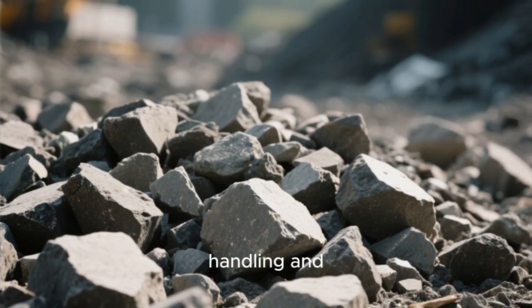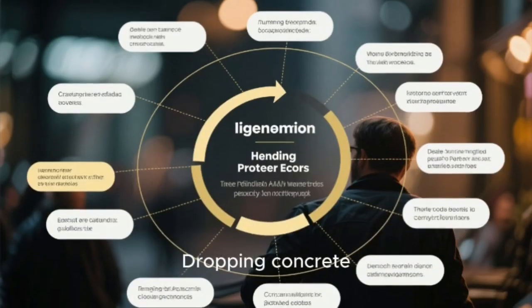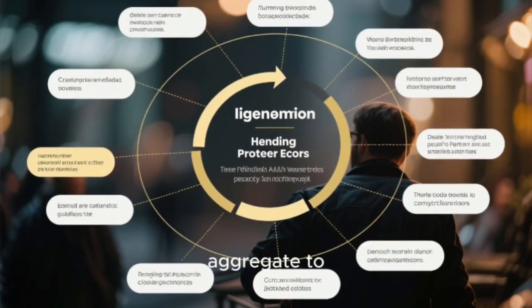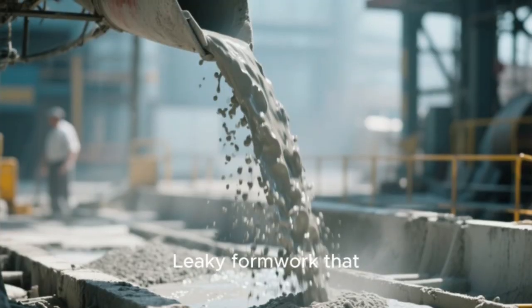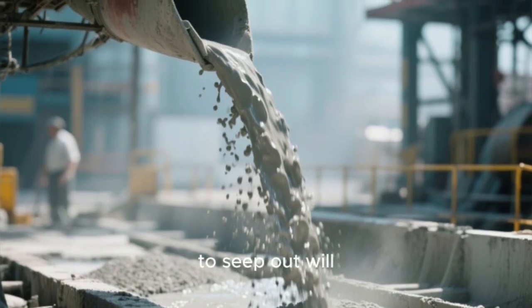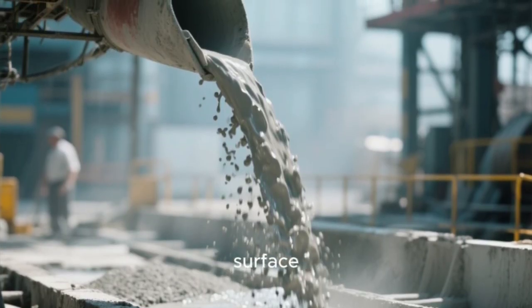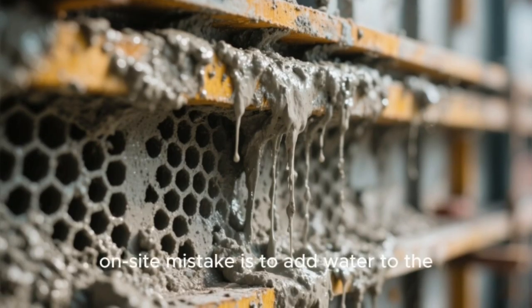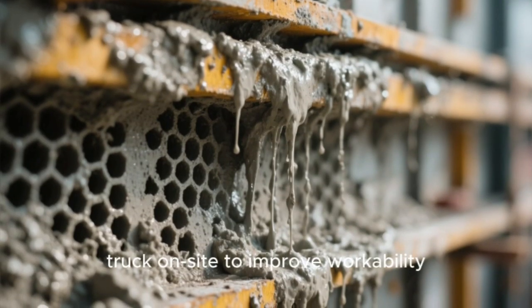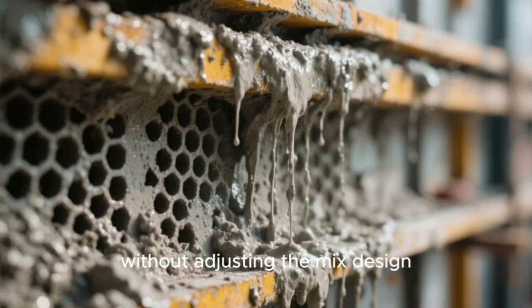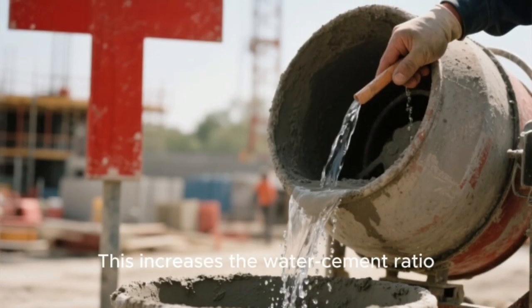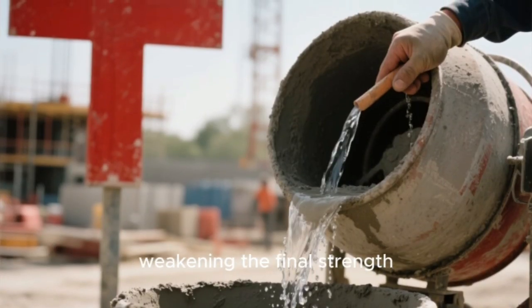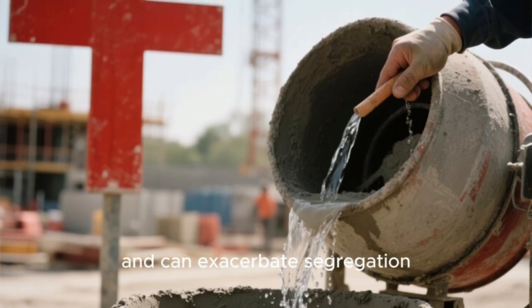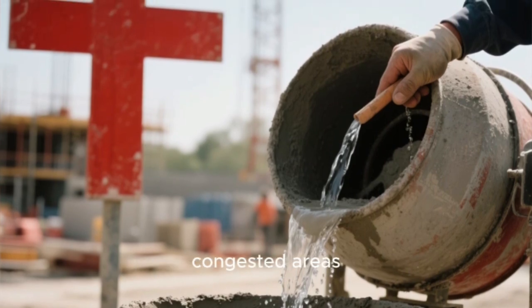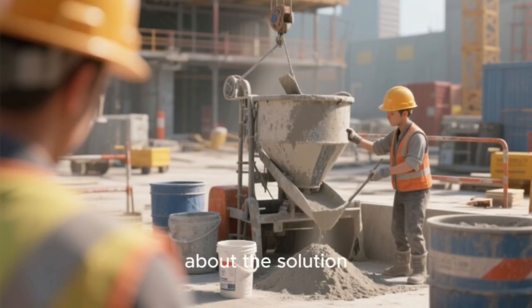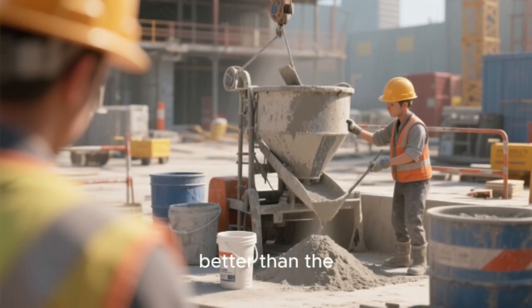The third category is handling and placement errors. Dropping concrete from excessive heights causes the aggregate to segregate from the paste. Leaky formwork that allows cement paste to seep out will leave behind a rocky, honeycombed surface. A common and catastrophic on-site mistake is to add water to the truck on-site to improve workability without adjusting the mix design. This increases the water-cement ratio, weakening the final strength, and can exacerbate segregation, making the problem worse in congested areas. Now, let's talk about the prevention, which is always better than the cure.